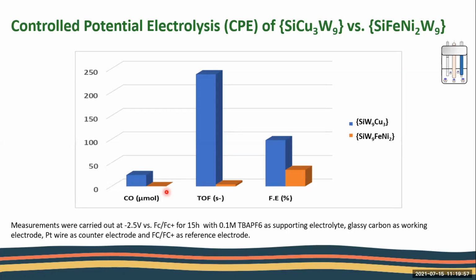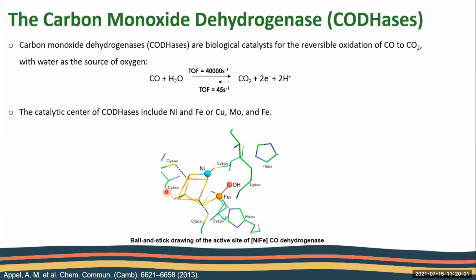So where are the products? That led us to think about a family of enzymes known in the literature, called the carbon monoxide dehydrogenase enzymes. This family consists of biological catalysts for the reversible oxidation of CO to CO2 with water as the source of oxygen. You can see here that the oxidation of CO to CO2 is much faster than the reduction from CO2 to CO. There are two types of this family. The first type includes nickel and iron in its catalytic center, and the second type includes copper, molybdenum, and iron in its catalytic center. So at this moment we thought, maybe in our iron nickel complexes, we produce the CO and immediately oxidize it to CO2. Because of that, we didn't see any product.